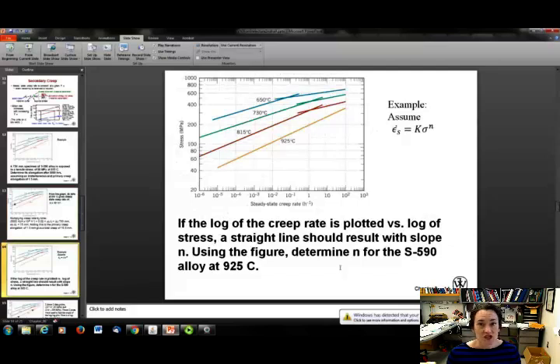Okay, here's another question, all right? These are all taken from your book. If the log of the creep rate is plotted versus the log of the stress, as it was previously, a straight line should result with a slope of n, okay? So using the figure, determine n for the S590 alloy at 925 degrees Celsius that's shown here in the orange curve, okay? So we're assuming that the temperature is held constant, so that exponential term e to the minus Q over RT, that's a constant value, okay?